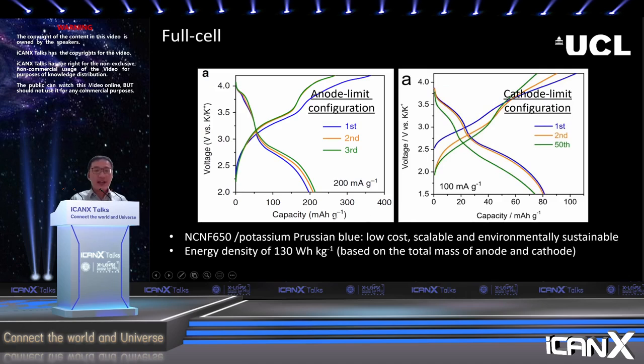And we calculate the energy density of these full cells, which is 130 watt-hour per kilogram. And this number is quite lower than the estimated number at the beginning of my talk. But considering it is a very preliminary work, I believe this work actually gave us a very positive signal that by using carbon materials, we can achieve low cost potassium ion batteries. We can easily scale up the synthesis of the material. And with the research development between the time the paper is published and now, I have seen there is a large amount of work focusing on carbon materials for this topic. And the performance of carbon materials has been greatly enhanced since this work was done.